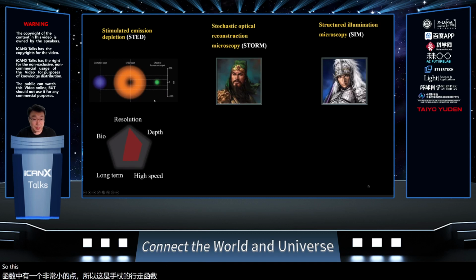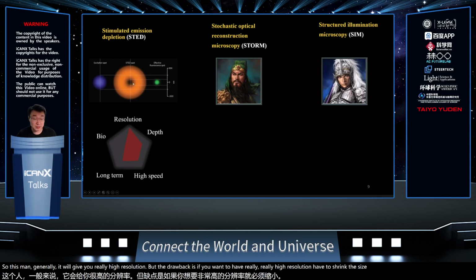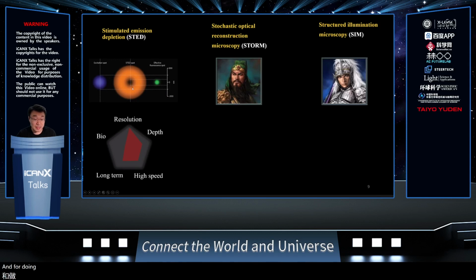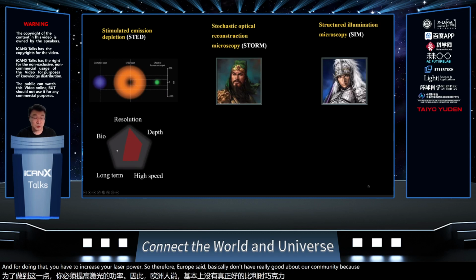This one generally gives you really high resolution, but the drawback is if you want really high resolution, you have to shrink the size of the middle hole. And for doing that, you have to increase your laser power. So therefore, usually STED basically doesn't have really good biocompatibility because you need to use high laser power.